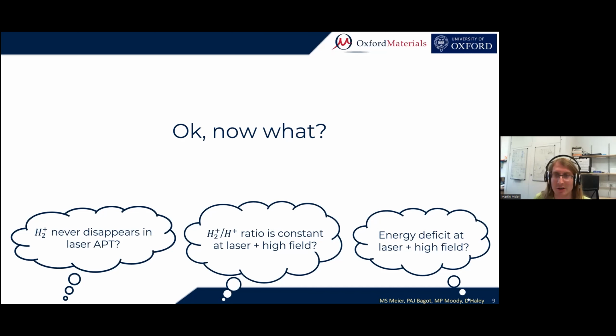And what experiment could we do in order to dig deeper and really find out what is going on in these tips? We came to the conclusion that the tungsten experiments that we have run so far were probably insufficient by quite a lot. Because the tungsten tips naturally run at a very high electric field, and as such, they can only confirm these observations that we make about the odd type of hydrogen at high fields in our archival data. But what we actually want, and what would be way more interesting, is a series of hydrogen spectra that we record at different electric field strengths.